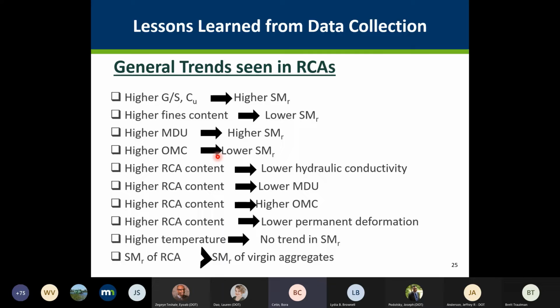And as expected, unlike RAP materials, an increase in temperature didn't seem to impact the resilient modulus of the RCA materials, because there is no asphalt binder in these RCA materials. So it was not surprising to see that higher temperature didn't impact the resilient modulus of these RCAs. And overall, what we observed, which we didn't have as clear with the RAP materials, is that the resilient modulus of RCAs was higher than the virgin aggregates, like the ones that we collect from quarries, the regular conventional aggregates' resilient modulus values.